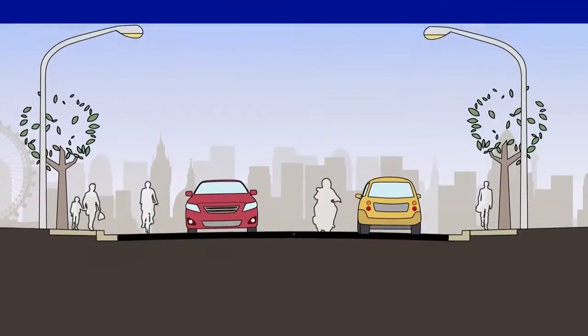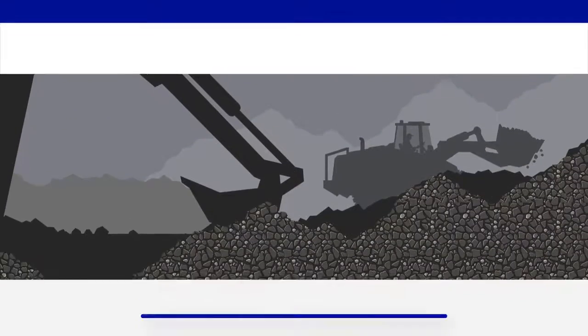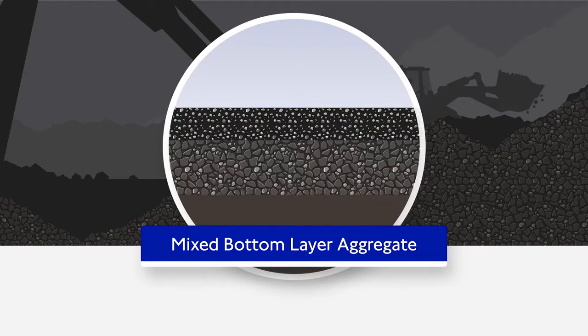When we actually remove an old road, we remove 100 millimetres all in one pass. That means you've got top layer aggregates and bottom layer aggregates that are mixed. Some surfacings in London would last around 20 years — you're throwing away an aggregate that still has life. Very good stone sitting on the surface, if it gets recycled, goes back in as a base material. That is a big waste because you are then using a high property aggregate into something that all it needs to do is provide structure and not surface properties.